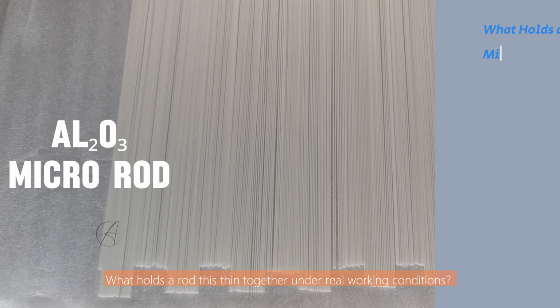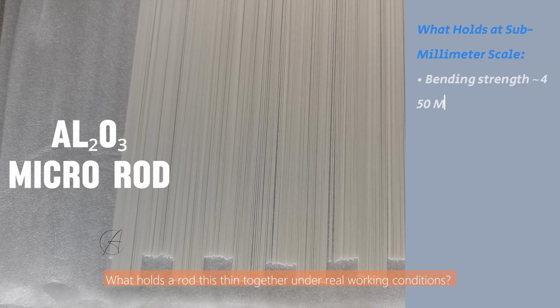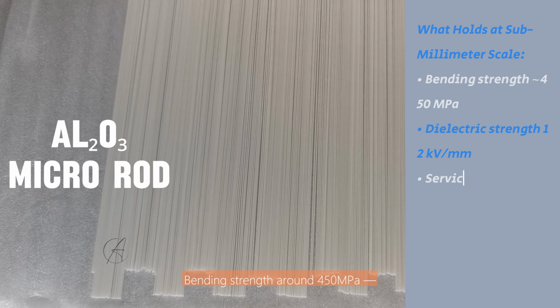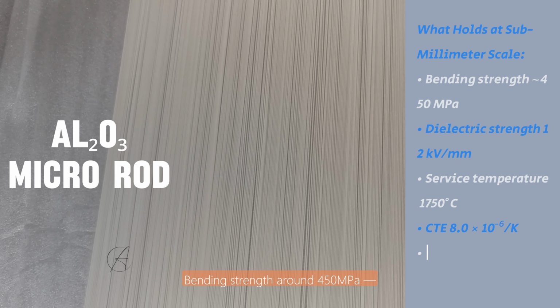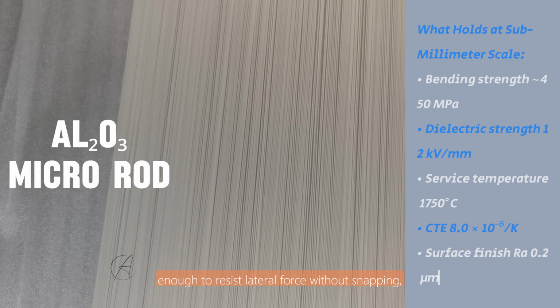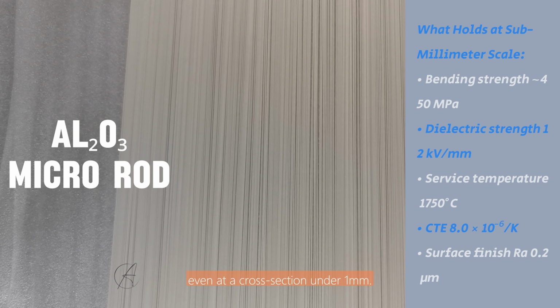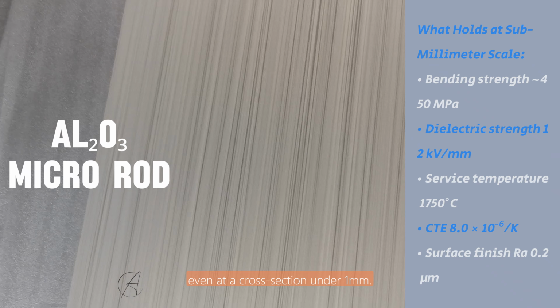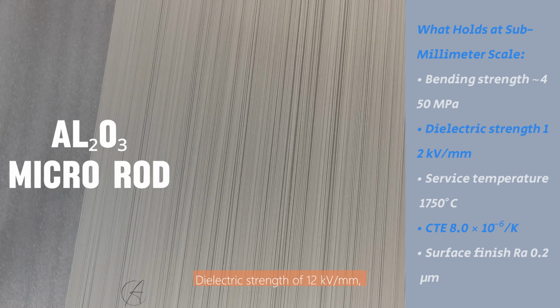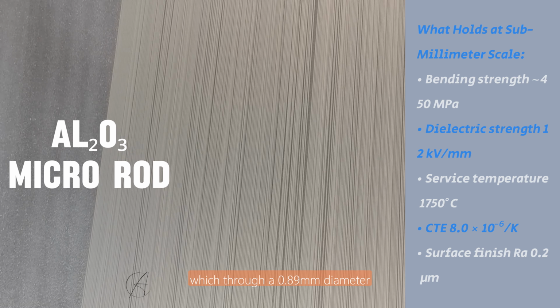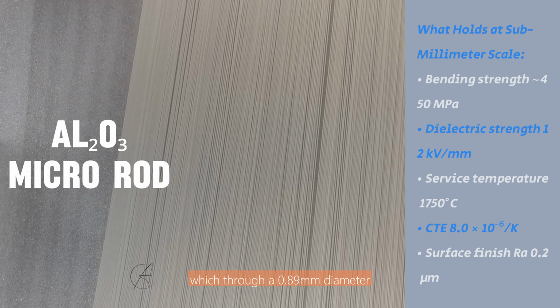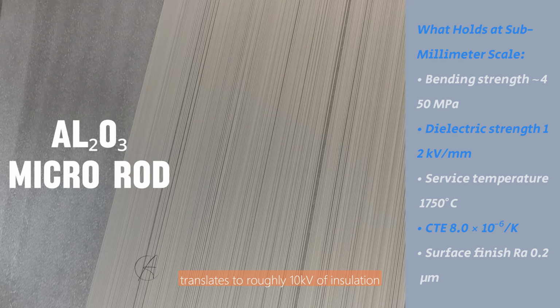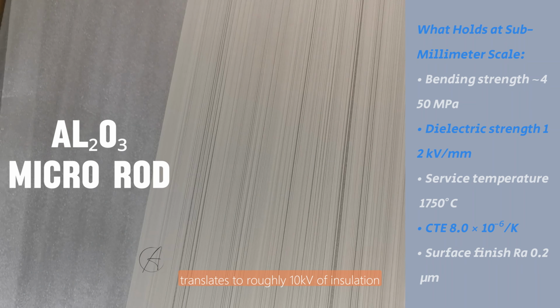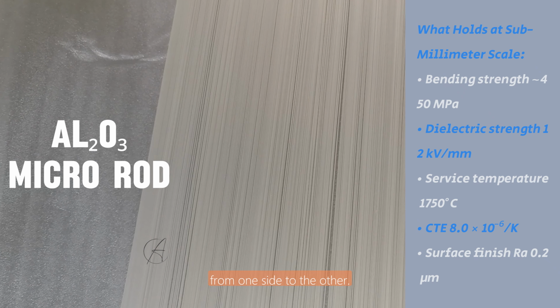What holds a rod this thin together under real working conditions? Bending strength around 450 megapascals, enough to resist lateral force without snapping, even at a cross-section under 1 millimeter. Dielectric strength of 12 kilovolts per millimeter, which through a 0.89 millimeter diameter translates to roughly 10 kilovolts of insulation from one side to the other.